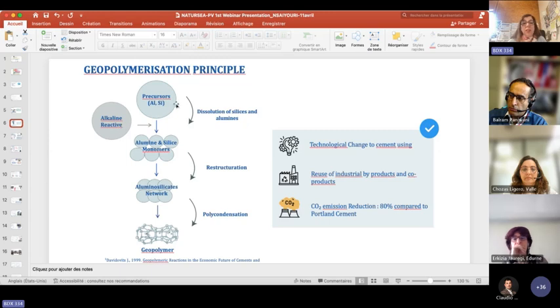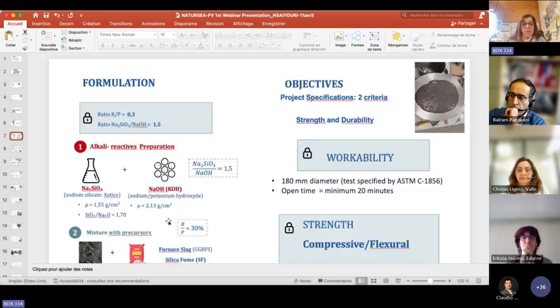The precursor and alkaline give dissolution of silica and alumina, and this alumina and silica go into monomers, which are restructured, giving a network of aluminosilicates. And after polycondensation, we obtain that geopolymer, which is strong and mechanically strong. Yes, it's a high mechanical strength, or at least compressive strength.